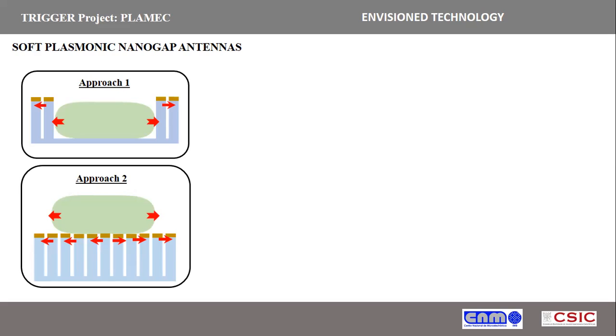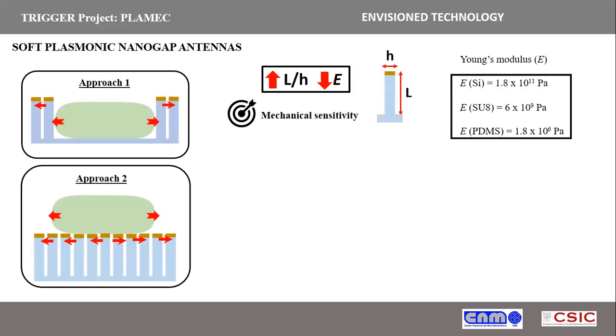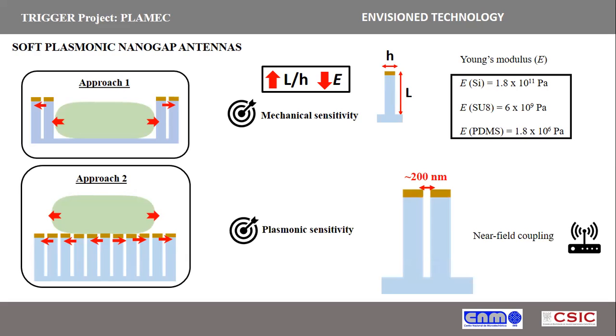Here we have to keep in mind that the performance of our system will be affected by both the mechanical sensitivity and the plasmonic sensitivity of the system. The mechanical sensitivity mainly depends on the aspect ratio of the antennas and also on their stiffness. Briefly, the mechanical sensitivity will be proportional to the aspect ratio of the antennas and inversely proportional to the stiffness, which is expressed by the Young's modulus of the material. Also, the plasmonic sensitivity is critical in our technology, which will be mainly determined by the gap distance between the antennas, which should be less than the diameter of the antennas, to allow a strong near field coupling between the antennas.